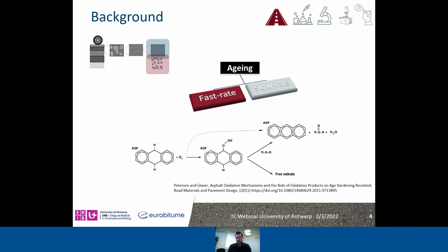For example, one of the most popular ones, proposed already around 20 years ago, suggests that a model compound of bitumen, in this case a dihydroanthracene, can react with oxygen, and after some intermediate products like hydroperoxide, can either decompose to organic free radicals or can be aromatized, and can also be accompanied by the formation of sulfoxides. This refers to the fast rate reaction, and the free radicals were considered to play an important role for the continuation of the second phase, which is the slow rate-determining phase.